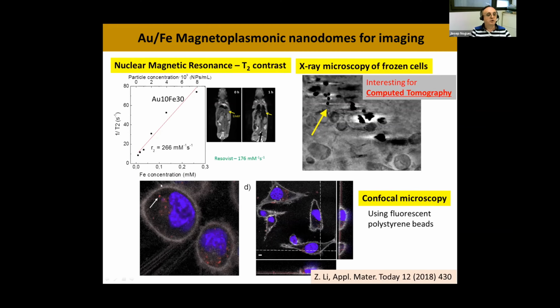Here I show you some confocal microscopy images of cells. This is a nucleus, with the red dots here inside are the nanodomes. And here in the computed tomography we can do a 3D scan, and here I showed you the projection of these cells, and you see that indeed the nanoparticles are absorbed inside the cells.